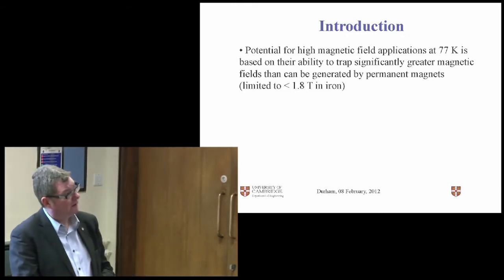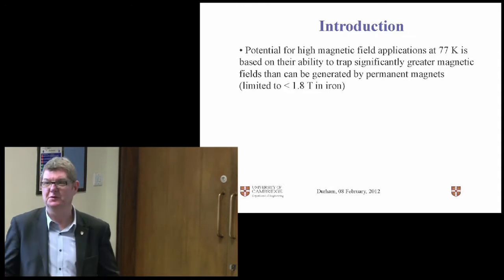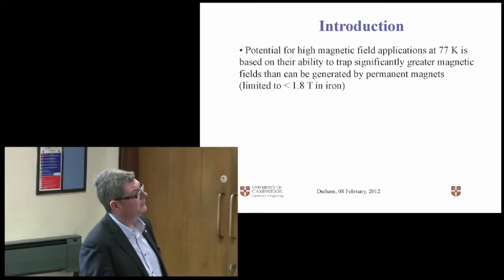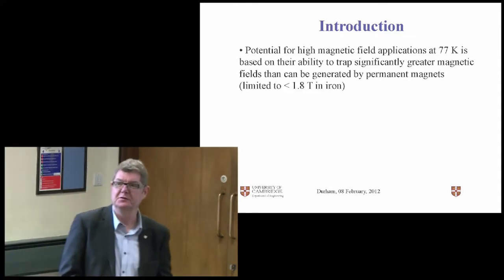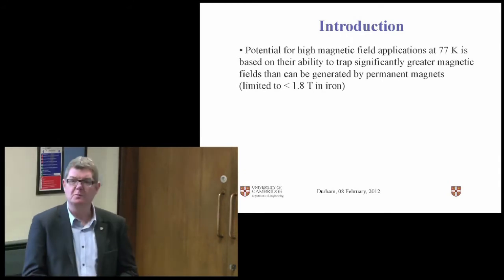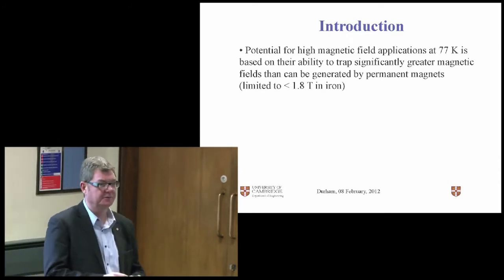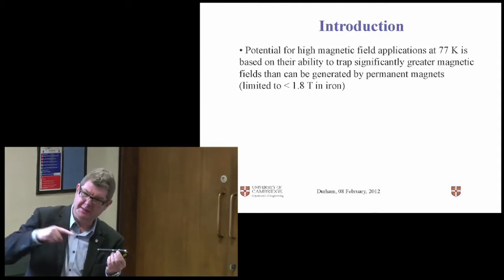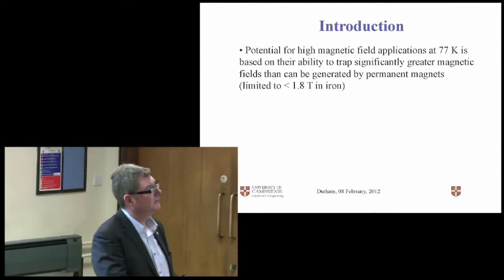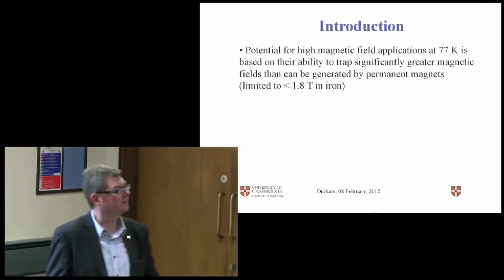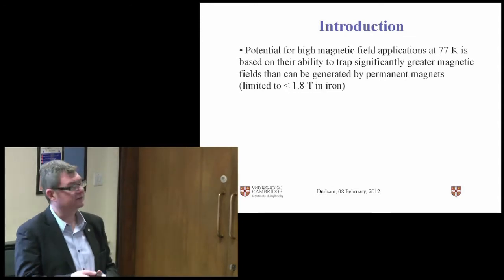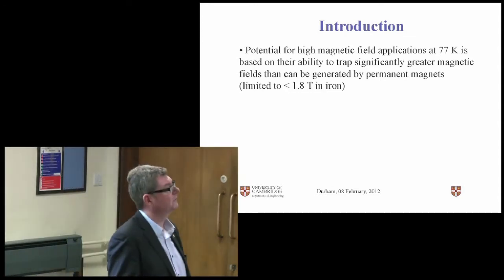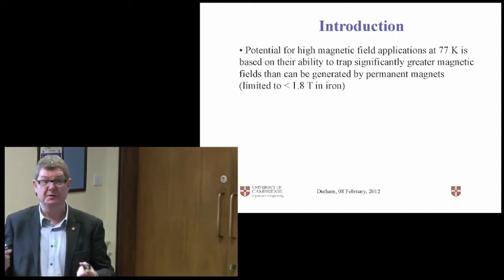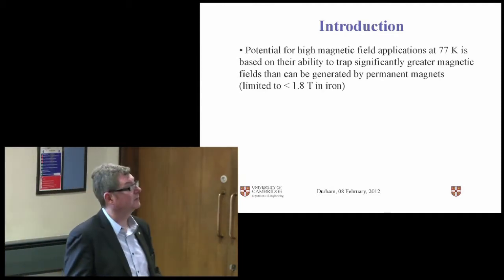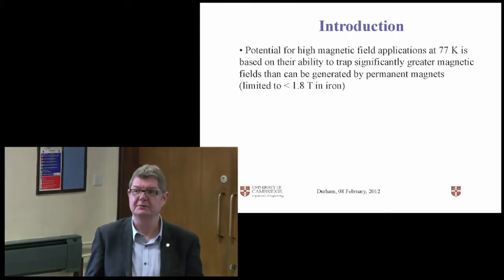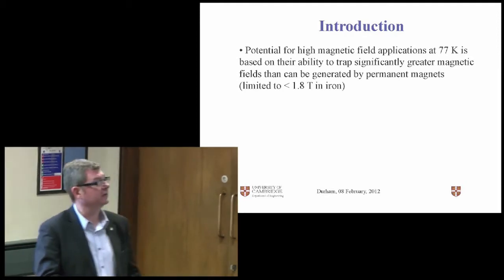These fields ultimately will be compared with what you can achieve using a permanent magnet. And interestingly, the best permanent magnet field you can get is a bit less than 1.8 Tesla. If you take iron in the form of a long, thin rod, and you magnetize it along its length, you can generate possibly 1.5, 1.7 Tesla. And that's how the Victorians used to make their magnets. But it's limited by the number of unpaired spins per site, 2.2 in iron, and there's nothing you can do about it in terms of processing. So this is an absolute limit.